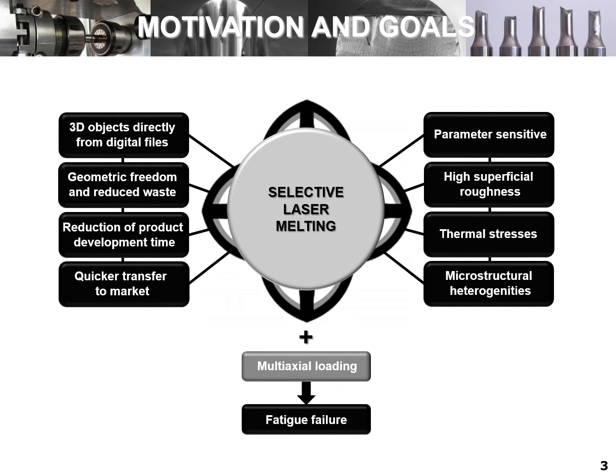Nevertheless, this technique is rather complex. Products are parameter sensitive and are very prone to microstructural heterogeneities, such as unmelted particles, cavities, pores, contaminations, etc. In the presence of cyclic loading, in some cases with a multiaxial nature, the SLM parts are susceptible to fatigue failure.